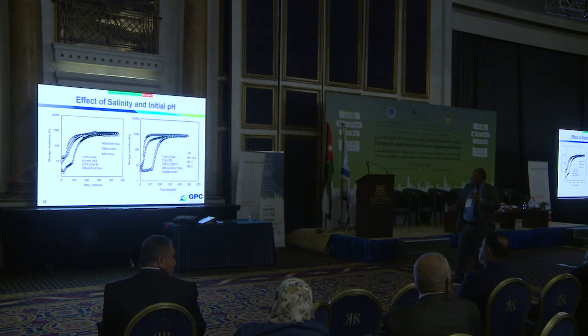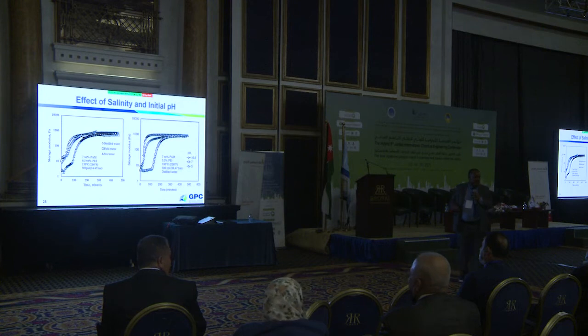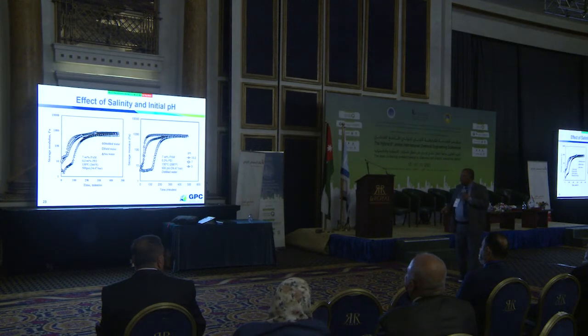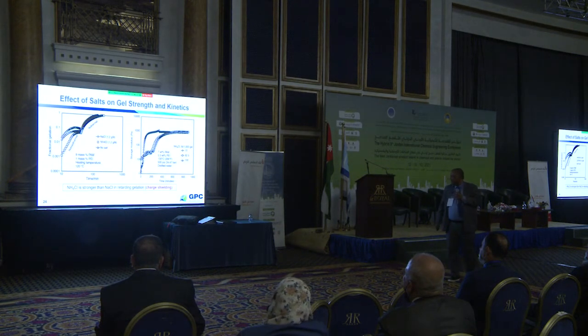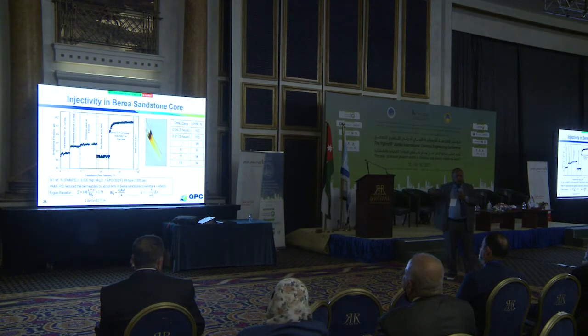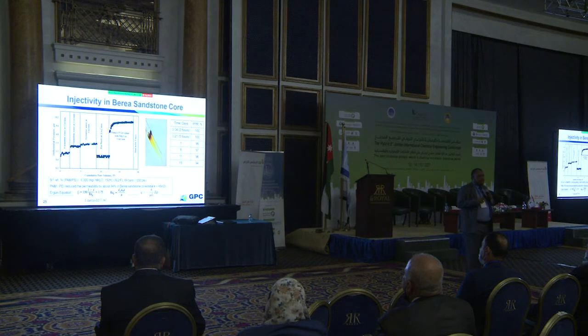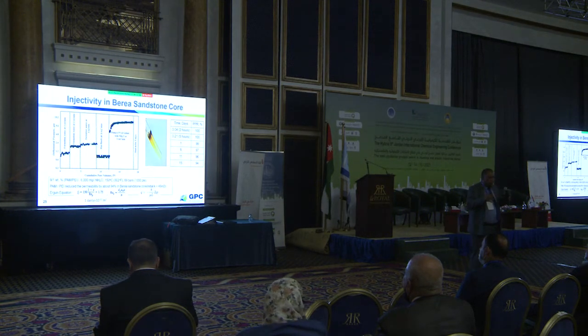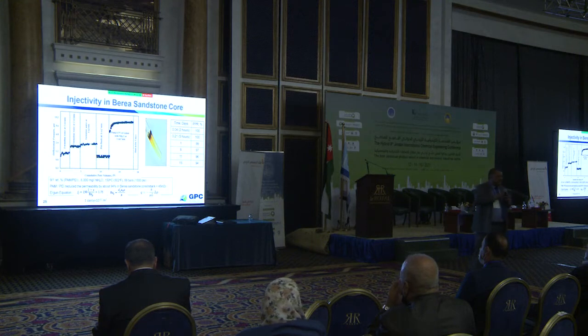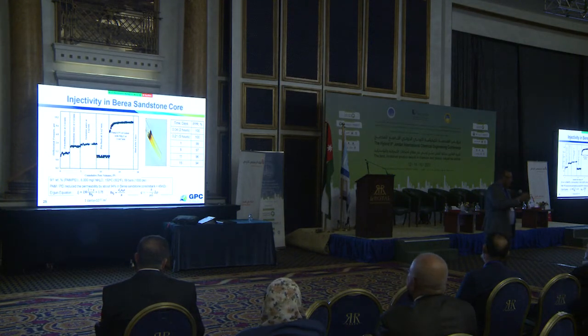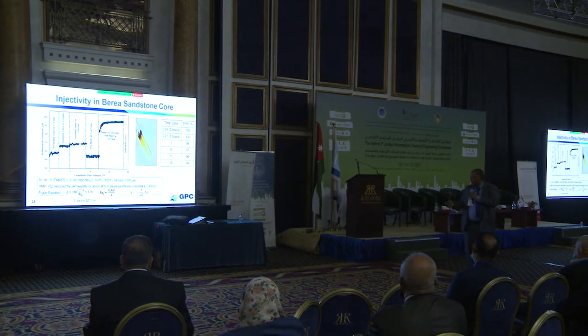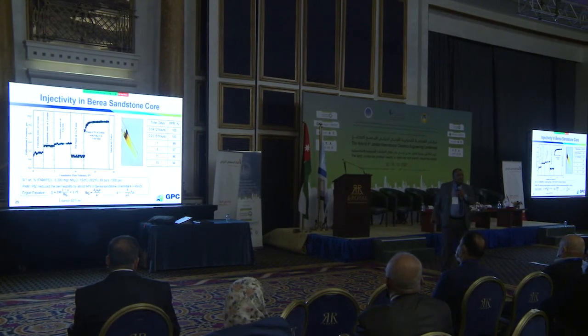Temperature and pressure also affect our study. Salinity is very important, especially since salts work as retardants. Some, like sodium chloride and ammonium chloride, are widely used to play with the gelation time. We tried this in the lab in some highly permeable rocks. We injected these formulations, gave them some time, similar to what happened in the field, and let them form a gel. After that we put water or another fluid at very high pressure to see whether the fractures or high permeability zones are sealed or not. And what you can see here on the right is the percentage of permeability reduction.